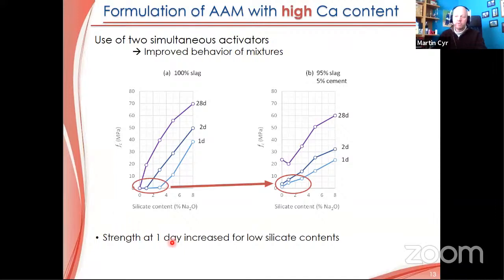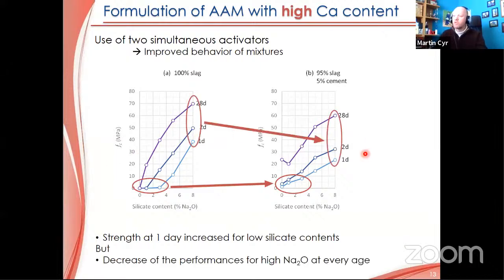We can reach very good strength at one day with this kind of material. Not very good, but correct enough for demolding. We see that when we shift from only slag with sodium silicate to a little bit more cement inside, we can solve some problems of demolding by increasing the strength at young age. So it can be very interesting, but sometimes we have a decrease of performance at longer term. We can see here at 28 days, we have a small decrease in performance. That's what we see when sometimes we put different activators together. So it's only to illustrate what we can do to solve some problems, but sometimes it will lead to other kinds of problems itself.